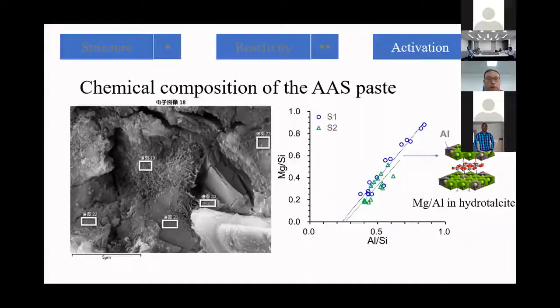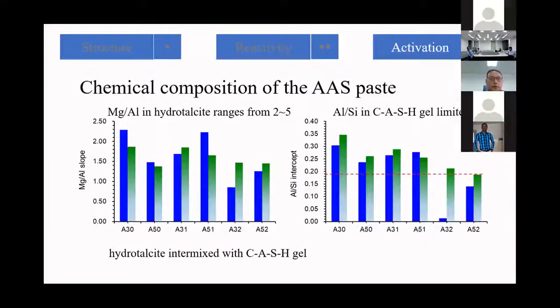By employing the EDX methods, we could determine the chemical composition of the pastes. This plot is the magnesium-silicon ratio against the aluminum-silicon ratio. From this plot, we could speculate the magnesium-alumina ratio in hydrotalcite, and also indicate the aluminum-silicon ratio in C-S-H gel. And these are the results.